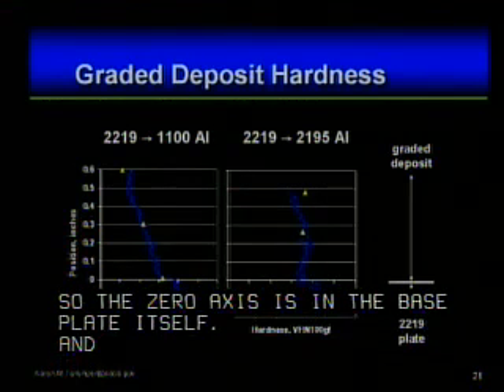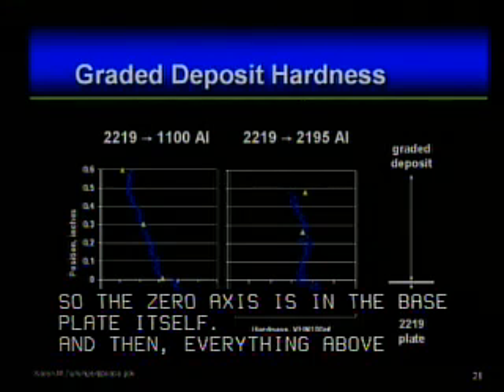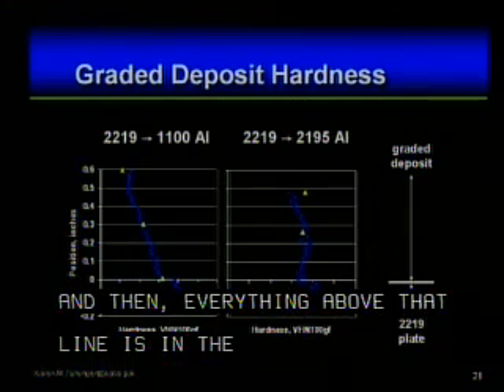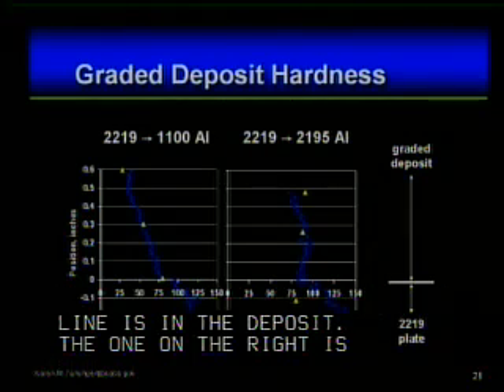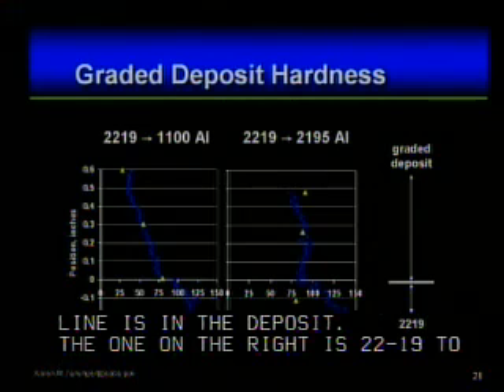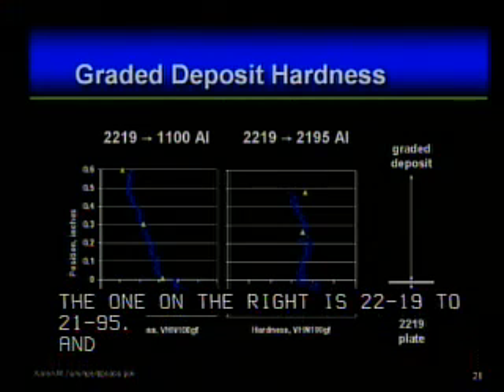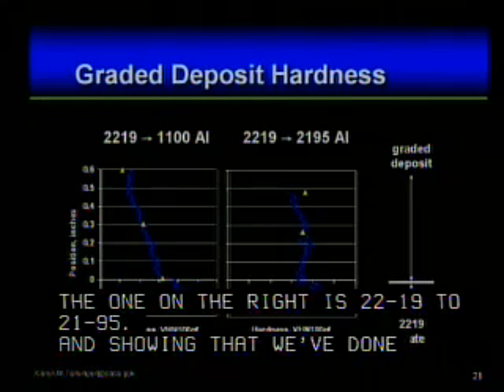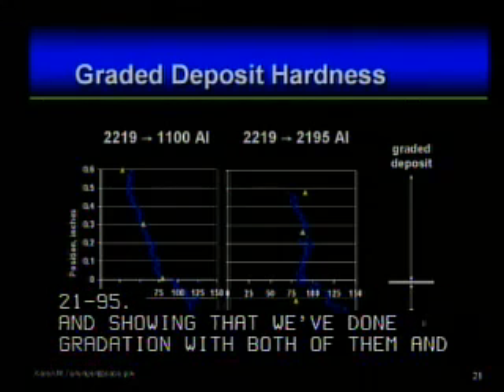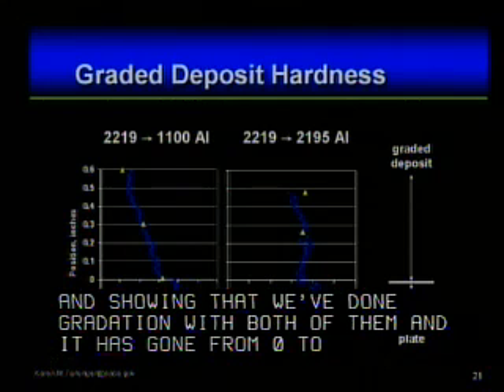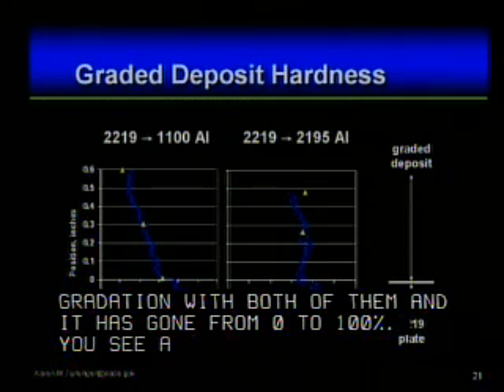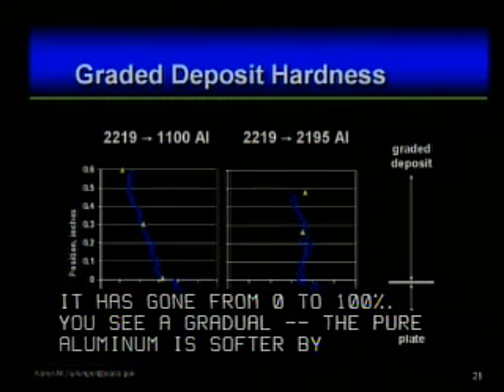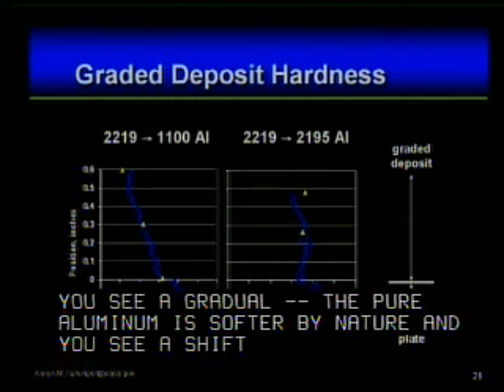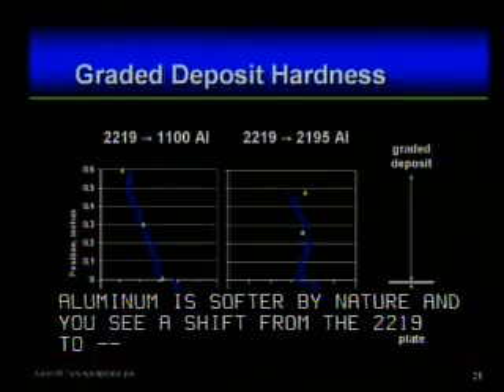I've got two graphs here. The one on the left is the 2219 to pure aluminum, or 1100 aluminum. The one on the right is 2219 to 2195. 2195 is an aluminum lithium alloy. So we've done gradation with both of them, going from 0 to 100%. What you see in the data is a nice gradual shift, since the pure aluminum is softer by nature, from the hardness in the 2219 to the hardness in the pure aluminum.